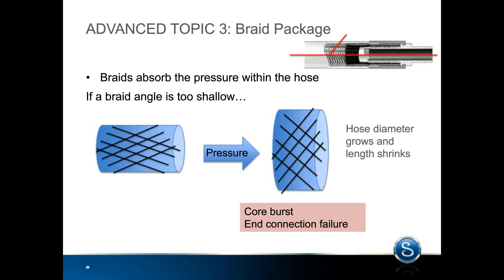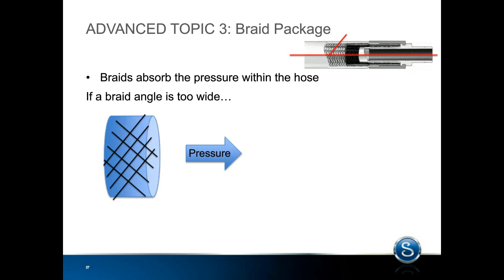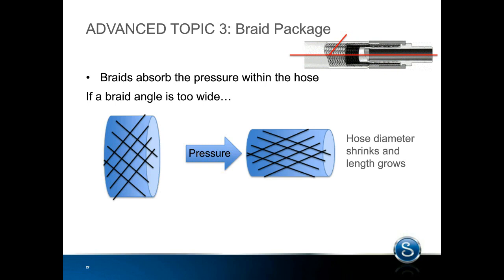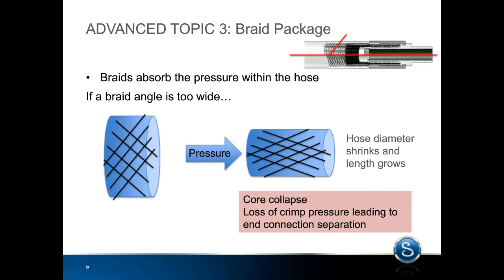Likewise, with a steep or too wide braid angle under pressure, this hose is going to do the opposite. The hose will crush the core tube. The braids will flatten out and crush the core tube, and the length will grow. Now, the length growing a lot of times isn't a concern, but crushing the core tube could collapse the core tube, and crushing the core tube can remove the crimp pressure. So if this is a crimped hose and you crush the core tube, you can lose the crimp pressure on the end connection, and the end connection could separate from the core tube, which again is a very, very dangerous failure.